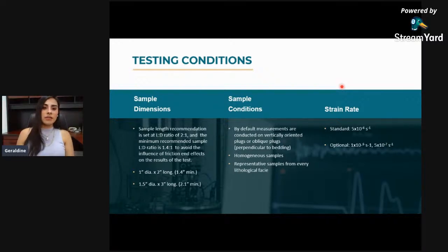The minimum recommended is 1.4, in order to avoid the influence of friction and end effects in the results of your testing. So this means that if I have a 1-inch diameter sample, the optimal length will be 2 inches, but the minimum could be 1.4. For 1.5-inch diameter samples, the optimal length will be 3 inches, but the minimum accepted is 2.1 inches. Length, sorry.